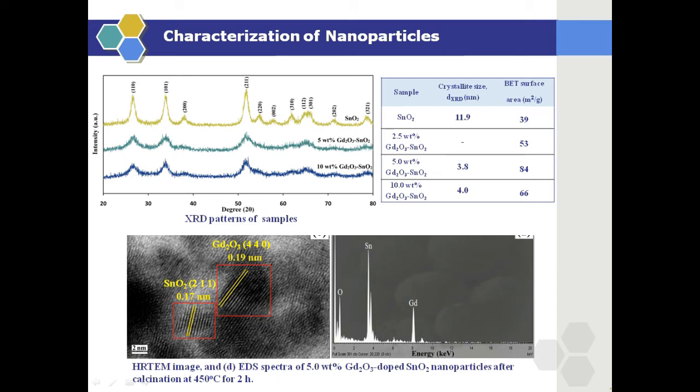In this condition, as the dopant concentration increases, the dopant-dopant interaction becomes important and results in precipitation of dopant nanoparticles. If dopant nanoparticles form precipitate rather than remain in the grain boundary, grain growth will occur.